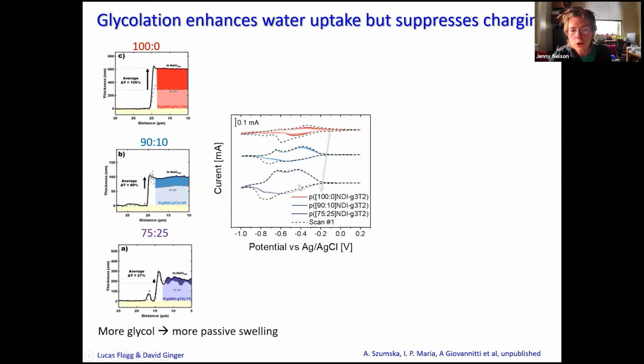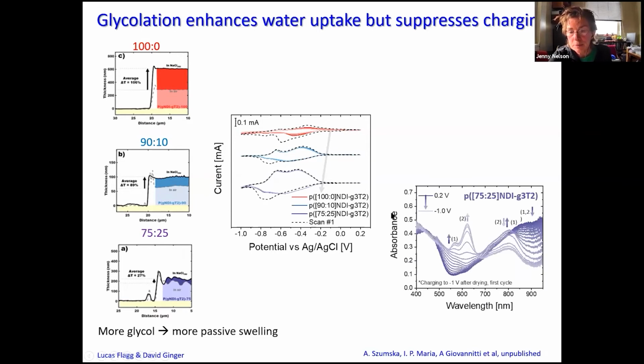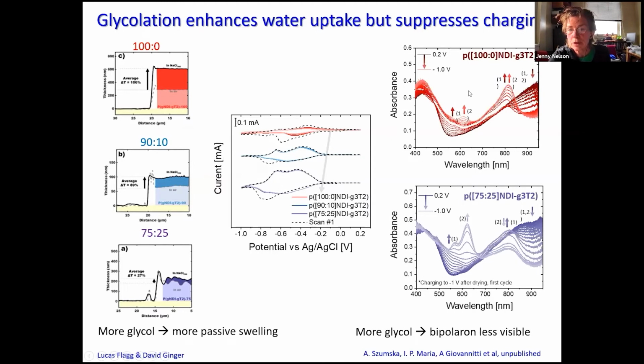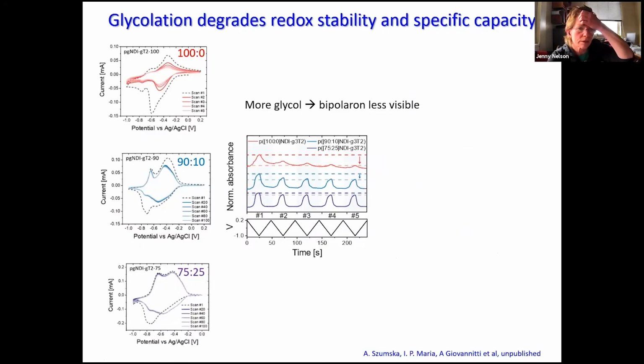We also look at the spectroelectrochemical properties, and as with the previous NDI-T2 polymer, we can see during cycling the very clear appearance of the bipolaron peak. That's very nice. This is for the 25% alkylated polymer. But for the fully glycolated polymer, we see the same features, but they're somewhat less visible. This was during the first cycle. So we decided to look at what happened during subsequent cycles.